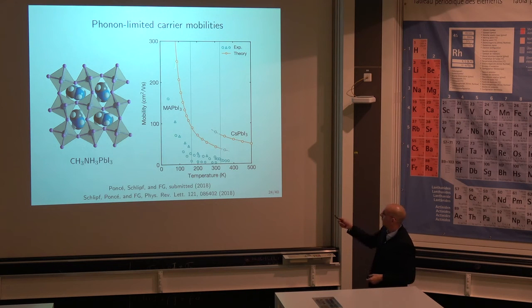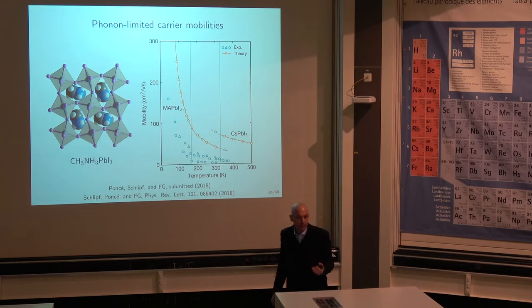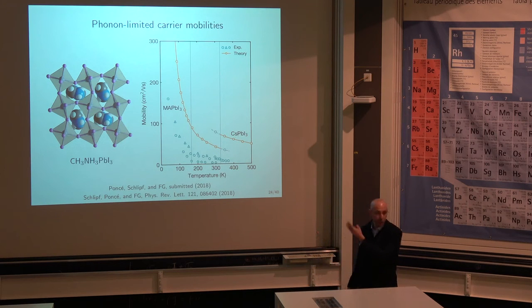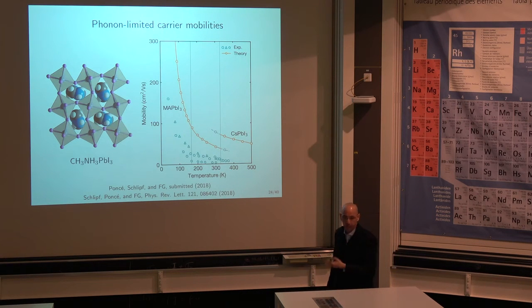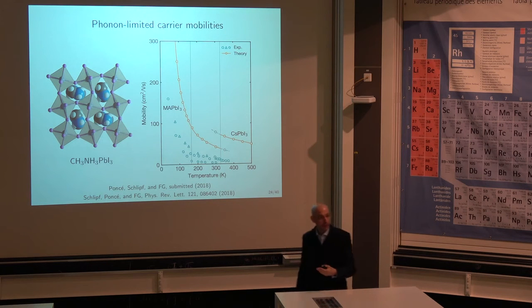And what you can see is that these are our calculations. They scale like in experiments, but we overestimate the experimental data. That is not too surprising because we are only including electron-phonon scattering. The experiments have much more stuff inside, for example, the scattering by defects, grain boundaries, and things like that.